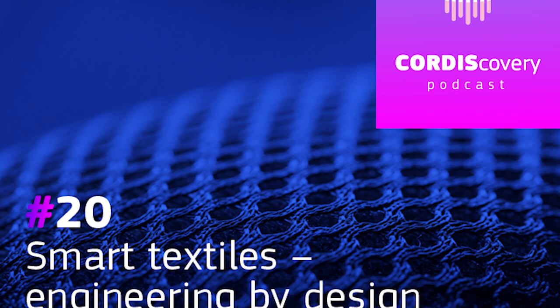So rather than, for example, adding wires into the textile, which can make the textile very stiff and heavy, our approach was to actually metallize the fibers within the textile to encapsulate them with a very thin layer of metal, and in that way introduce conductivity. So the idea was to produce a multifunctional material. Because we only produce this very thin layer of metal, the textile retained some of its properties, such as being flexible and light, but we've now also introduced conductivity and sensing abilities, for example.